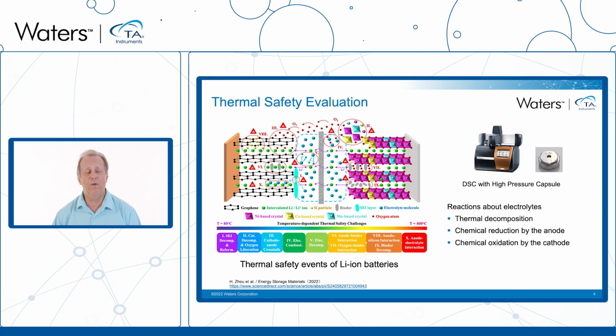And then we come to the cathode, which is typically a lithium metal oxide material, again, a layered material like graphite, which allows the lithium ions to intercalate into the interstices. And this is also coated onto an aluminum foil as a slurry, again, having polymer binders and some other conductive materials in it. Along the bottom, we see some of the things that can be thermal safety challenges within these batteries. I'm not going to go through every single one of them here, but starting at the low temperature end, there is the decomposition of what's called the SEI layer. That's the solid electrolyte interface, which is something that develops as you initially charge cycle the battery. It's a protective coating that ends up coating onto the anode.